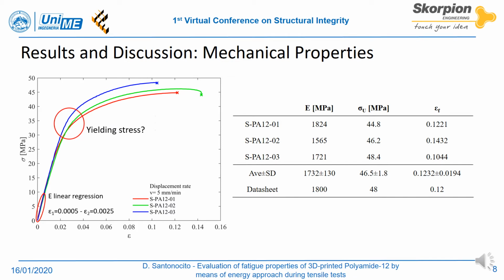Considering the value of the mechanical properties for PA12 Type 1 specimens printed with fast profile along XY direction, as reported by the manufacturer datasheet, it is possible to note how they fall within the range of the average and 1 standard deviation for the 3 tests. The mechanical properties are also in agreement with other authors who investigated PA12 obtained by laser sintering and multijet fusion system.